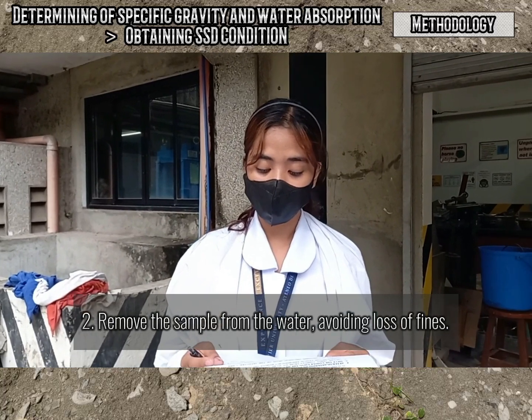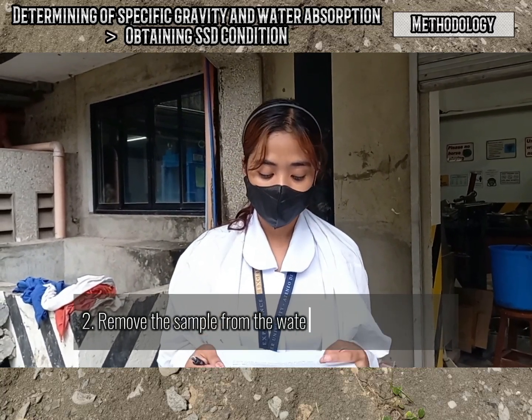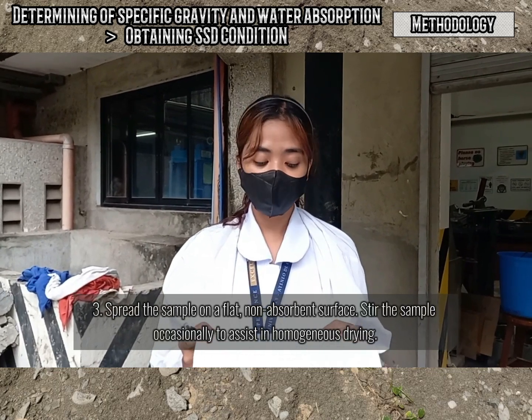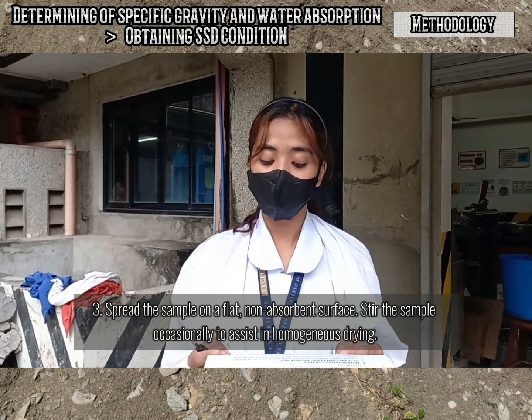Remove the sample from the water, avoiding loss of fines. And then spread the sample on a flat, non-absorbent surface, and stir the sample occasionally to assist in homogeneous drying.